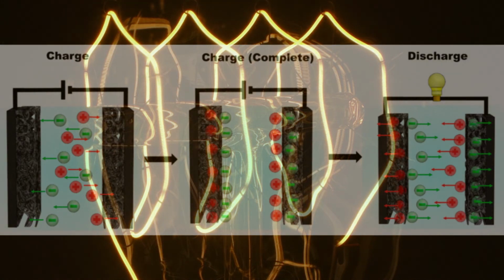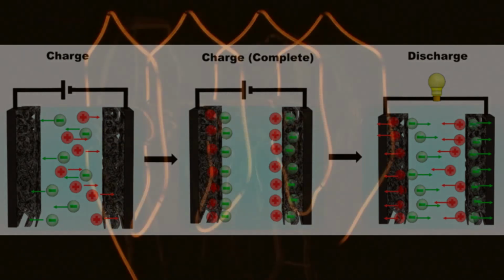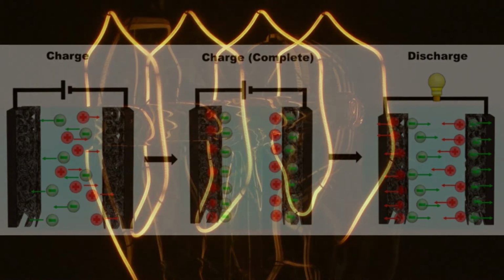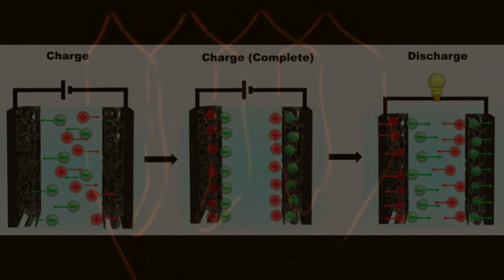storage. To fabricate these devices, a biscrolling process trapped poly(3,4-ethylenedioxythiophene) polystyrene sulfonate, PEDOT:PSS, ferritin nanoclusters in multi-walled CNT, MWCNT, sheets which are electrically conductive and have high mechanical strength. The multi-walled CNT sheets used were taken from a spinnable multi-walled CNT forest grown via chemical vapor deposition, CVD.